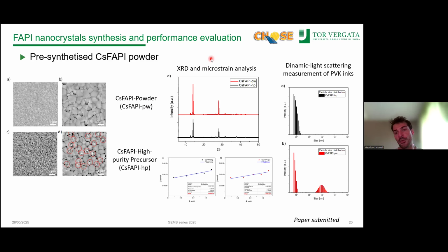Another peculiar thing that we saw, doing dynamic light scattering measurements on the two perovskite inks, is two different populations. For the high purity precursor, we can see only one population peaked around 1 nanometer, which is the dimension of the colloids present in the solution. But when we dissolve the cesium FAPI pre-synthesized powders in our solvent system, we have two different populations: one peaked at 1 nanometer, as usual, and the other one peaked at 100 nanometers. So we speculate that the size of the colloids inside the solution can have an impact on the deposition and on the crystal quality, and especially for our process, this may behave in a good way to get a nice and compact film that dissolving only the high purity precursors does not.